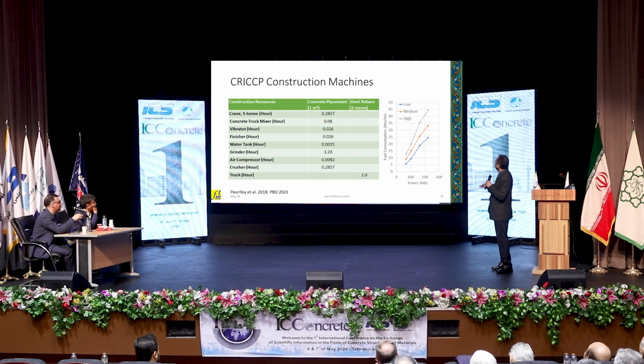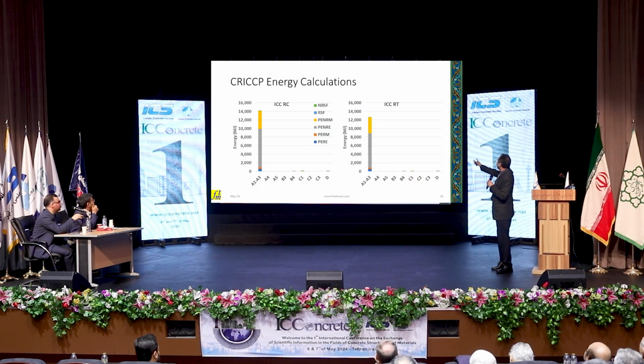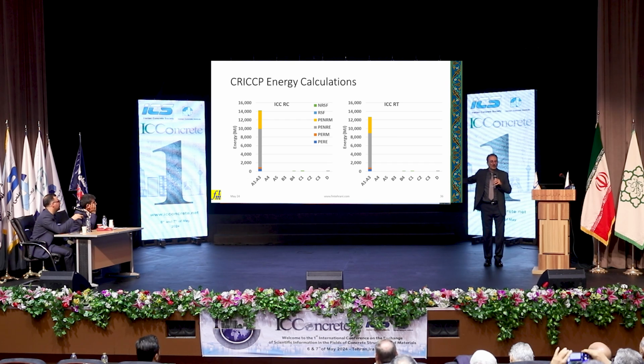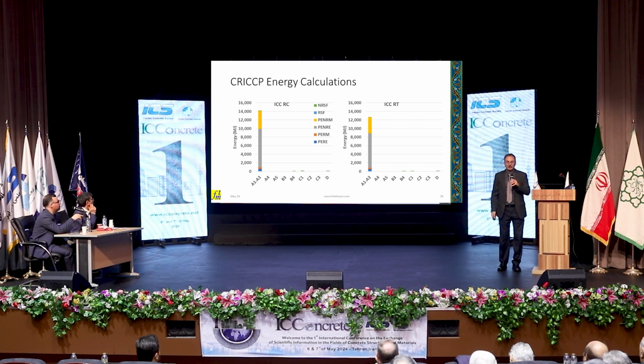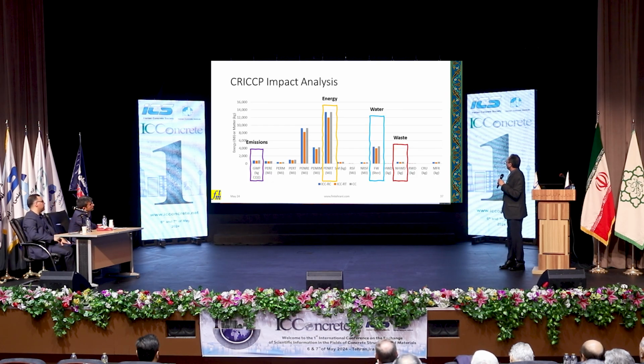And after doing all the number crunching, we get to this. So you can reduce the cement. If the strength of concrete is going to go higher, well, you can reduce the amount of cement, 50 kilograms per cubic meter. Why not? Number two, you say, no, I want to keep the cement. That's fine. Reduce the thickness of the slab. Either way. Dr. Tehrani, only 2 minutes, thank you. Of course. This is the reduction in emission, energy, water, and waste.